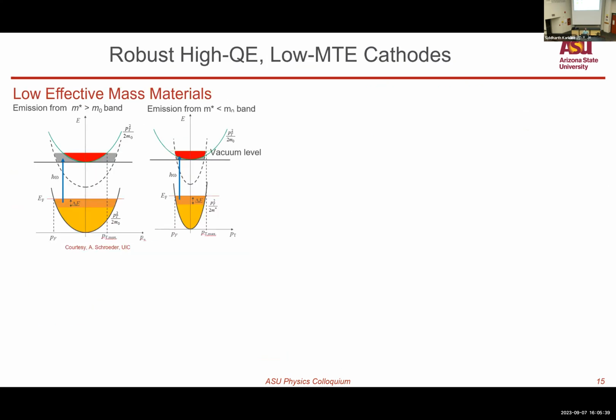Okay, now these cathodes again have a problem. These thin film alkali antimonide materials exist only in ultra high vacuum conditions. Even in high vacuum conditions, they oxidize pretty much instantly. So it would be really nice to be able to discover robust, high quantum efficiency and low mean transverse energy materials. One approach towards that is to use the low effective mass of materials, or low electron effective mass.